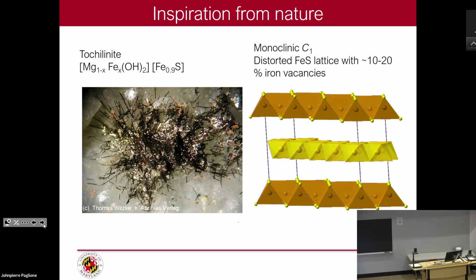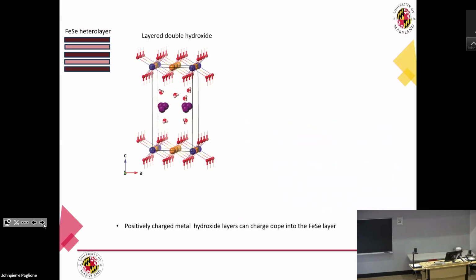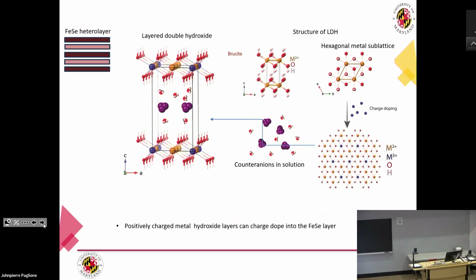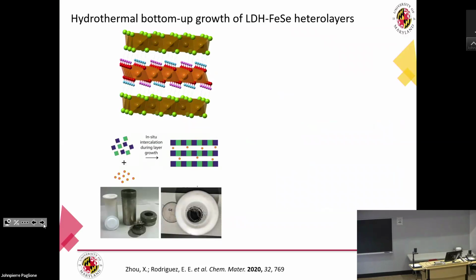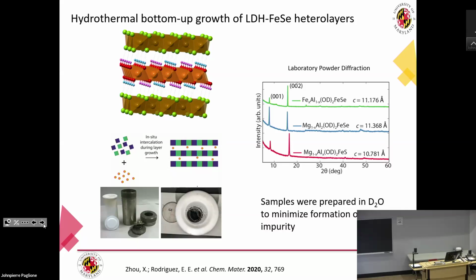As you can see, these nice golden flakes are growing here. And what we've done is use that idea to grow these iron selenide heterolayers, where you take that hydroxide layer. These are positively charged, so you can fill them with water, carbonates, all kinds of anions, chlorides. But instead of filling them with those anions, we're going to fill them in with iron selenide anionic layers. And again, we grow these hydrothermally to make these compounds, and we can make the iron aluminum, magnesium aluminum, selenides,